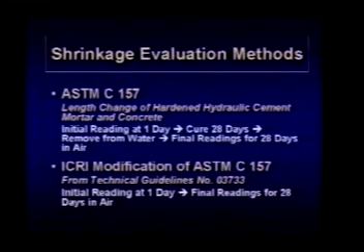And in fact, it's recommended to extend this to 56 days. And you can usually see your first 28 days is when you get your most shrinkage. By 56 days, the curves start to taper off. And it's the magnesium phosphate chemistry. Inherently, it's different from cement. It has an inherent chemical reaction which causes it not to shrink. It's a completely different chemistry.